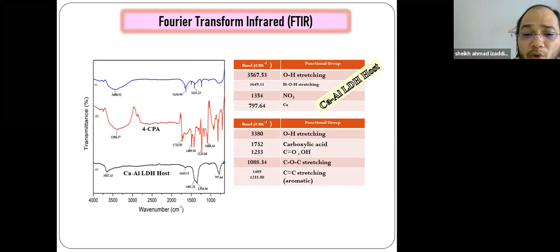So the calcium aluminum host has a broad peak corresponding to OH stretching at 3567, and a band appeared as a bending vibration of water molecule. So the calcium aluminum 4-CPA nanocomposite, as shown in the figures, indicates that the nitrate peak from the previous result, which was at 1354, disappeared and showed the 4-CPA, and it shows that the 4-CPA was successfully integrated with the layer. Okay, so next.